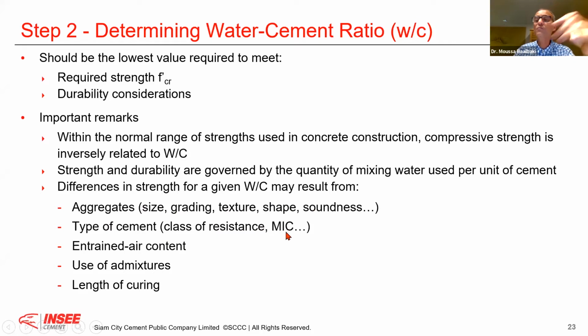If you don't use mineral components, for example, you don't develop enough strength. If you are entraining air, if I have 2% or I have 5% of air, it's not the same. Because the more air I put, I will lose strength. Use of admixtures, I can use some admixtures, and in this case, I can really reduce my water cement ratio. And the length of curing, strengths develop with time.